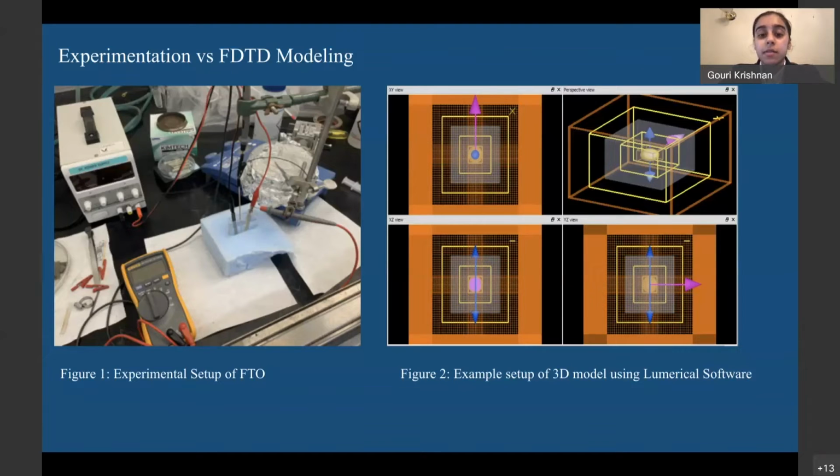After the growth of thin film, we subjected each sample to an applied electric potential, starting with a voltage of -3 volts. If no color change was observed, we increased potential by half a volt and repeated the observation process. This was done until a maximum of 3 volts of potential was reached.